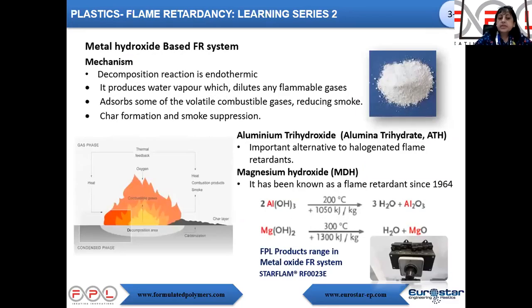The basic mechanism is decomposition, where it's an endothermic reaction. It produces water vapor, which dilutes the flammable gases. And of course, there is some adsorption so that the combustible gases are reduced and smoke also gets reduced. The protective mechanism is the char formation and the smoke suppression. Here we have given a couple of examples. The main thing here is that there is water which is released. So whether it's the aluminum trihydrate or it's the magnesium hydroxide systems, in both the cases, water is released. And if we consider the FPL products, then we have the magnesium based system, which is RF0023E STARFLAM grade.